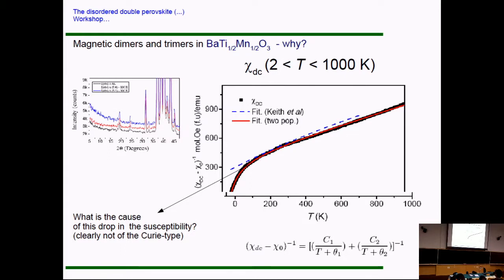And what called our attention at first was this huge drop here in the susceptibility, and we could not observe... this is field cooling, zero field cooling. We saw no hysteresis and no other sign of a phase transition. At this temperature, at least, you cannot actually miss a phase transition, right? So we simply started asking, okay, what is happening here?